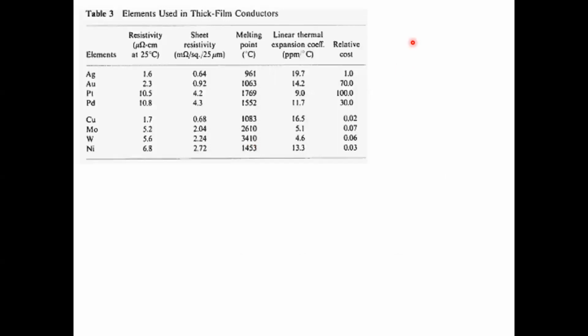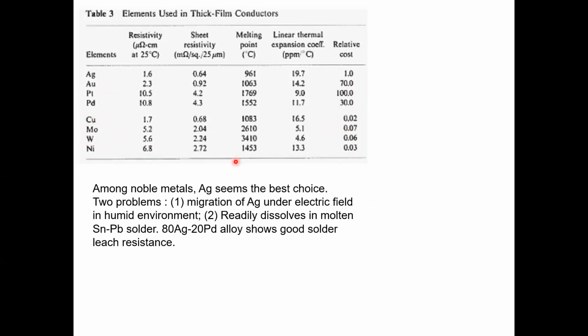In terms of electrical conductor material, you have all kinds of choices. Obviously, we use noble metals for the obvious reason: silver, gold, platinum, and palladium. There are various parameters: resistivity value, sheet resistivity, melting point, thermal expansion coefficient, and particularly the price. If you take silver as unit price, gold is going to be more expensive, and platinum will be even more expensive. So you can use other metals as electrodes like copper, molybdenum, and so on, and price-wise they look very attractive. But then the problem would be oxidation, for example. So there are a couple of issues. Among noble metals, silver seems to be the best choice, particularly for low temperature.